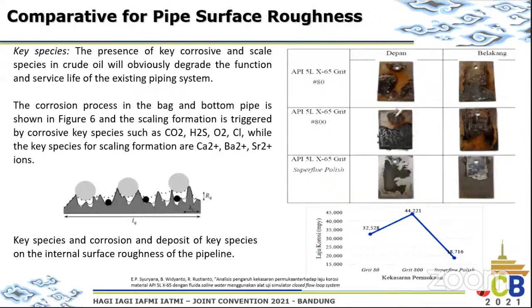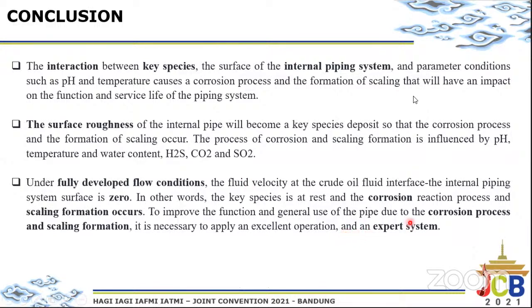Based on what I described before, maybe this applies especially for crude oil. We know we use ASME B31.4, and this is the comparison of the effect of surface roughness with the characteristic of many impurities I mentioned before. Scale basis has an effect on deposit in the characteristic of surface roughness. In our research before, we compared API 5L X65 with grit 80 and the surface characteristic from grit 800, and also a superfine finish. This is the characteristic of the surface corrosion product. I ran a test with the team using the corrosion flow loop system. And this is the conclusion. We know the effect of the fully developed velocity and the slow velocity at the surface of the pipelines. And this is the reference. Thank you, everyone.